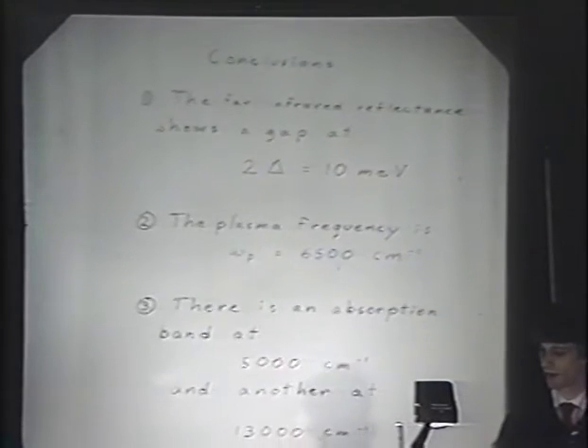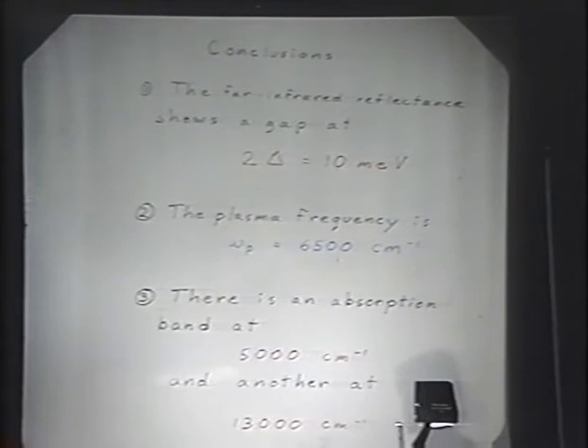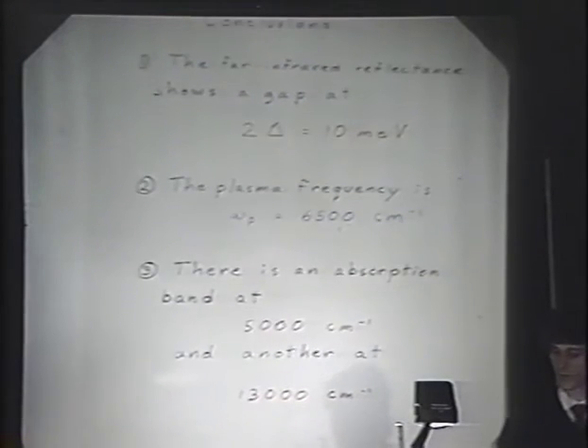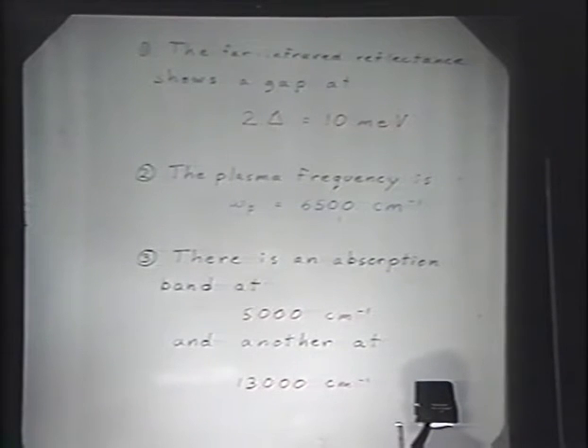So briefly in conclusion, we measure the far infrared reflectance as showing an energy gap somewhere on the order of 10 millielectron volts, a plasma frequency of about 6,500 wave numbers, and there are two broad absorption bands at around 5,000 wave numbers and 13,000 wave numbers. Thank you.